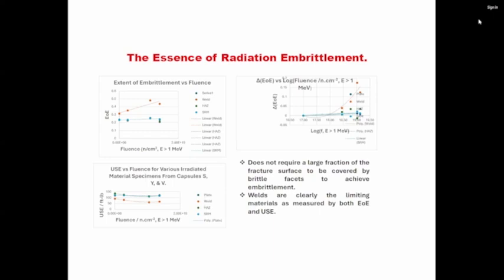And this appears consistently, not only in my calculations, but also in calculations that have been shown by other people. The important thing here is that it does not require a large fraction of the fracture surface to be covered by brittle facets to achieve embrittlement.